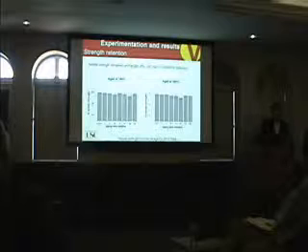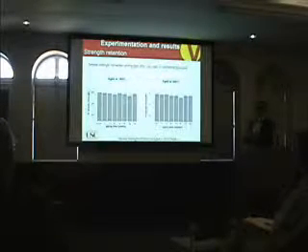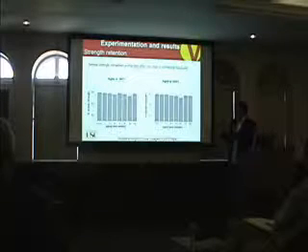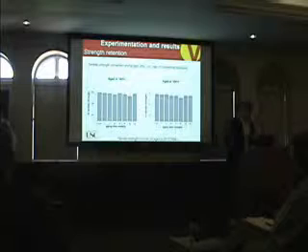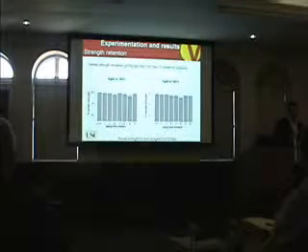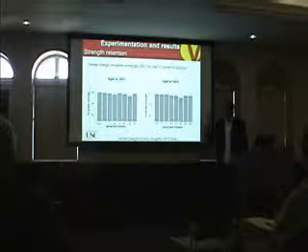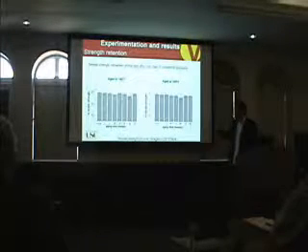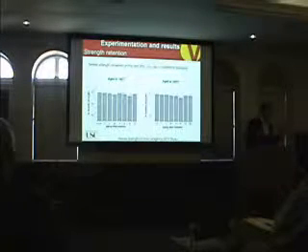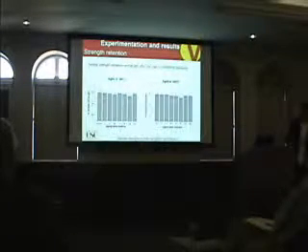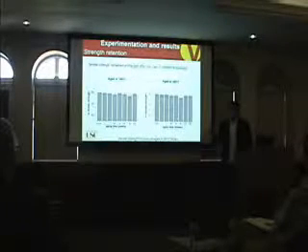One of the important mechanical properties that the industry is dealing with is basically the tensile strength of our material. We put our material for 1 year in the oven, and then we did the tensile test at 180 degrees C and 200 degrees C. And you see the tensile strength is almost constant, which means that the oxidation didn't affect the tensile strength of our material.